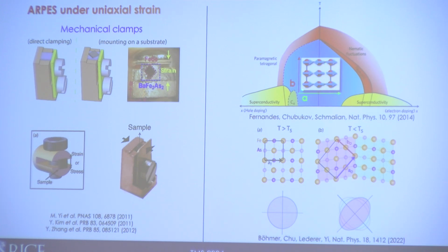So the spins order ferromagnetically along this axis and antiferromagnetically along the orthogonal axis, right? So you can already see that this breaks rotation, that has broken rotational C4 symmetry. So what that means is that in some of the doping regime, you actually first enter a structural transition that marks a boundary of what's called the nematic order, where the rotational symmetry is first broken, and then enter this magnetic order phase. So this is a very interesting phase that's basically very universal across many iron pnictide families,